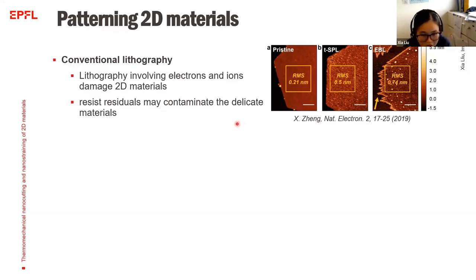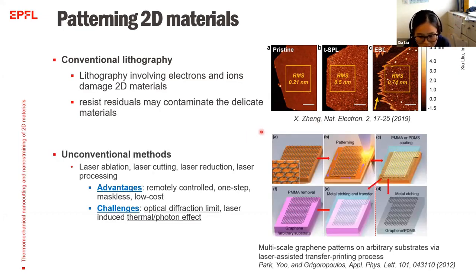Besides the conventional methods, many unconventional methods have been developed, such as laser ablation, also called laser cutting, laser reduction, and laser processing. The obvious advantage of the laser method is that it is remotely controlled, non-contact, and a one-step method. We don't need any mask, and the cost is low. Here shows an example of laser ablation. They use a laser to destroy or cut the graphene, and then transfer the cut material to any other substrate by the dry transfer method.